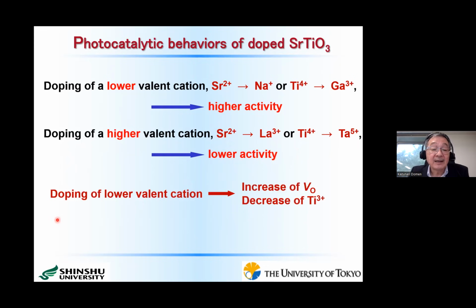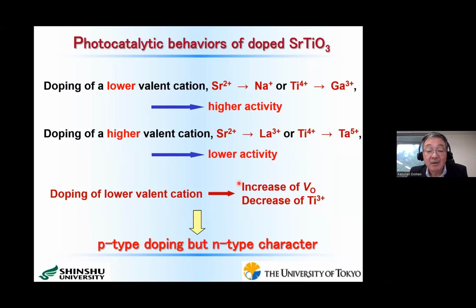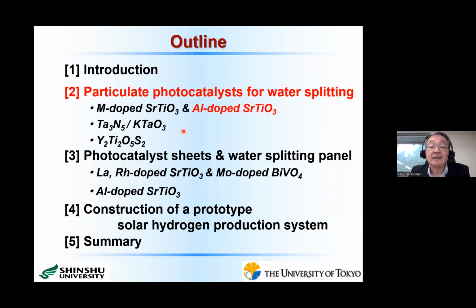So doping of lower valent cations tends to increase oxygen vacancies or decrease titanium 3+ cations if they exist in our strontium titanate. But discussion about the origin of this type of activity change is a little complicated. So today let me just say that although this kind of lower valent cation doping is so-called P-type doping, our material still shows N-type character. Okay, so let me now move to a more concrete example, aluminum doped strontium titanate.